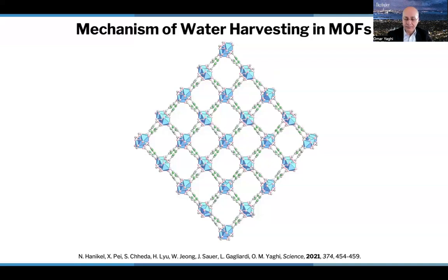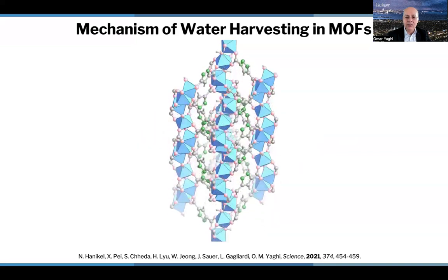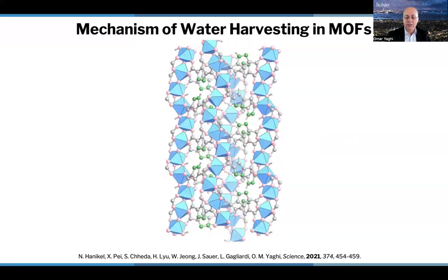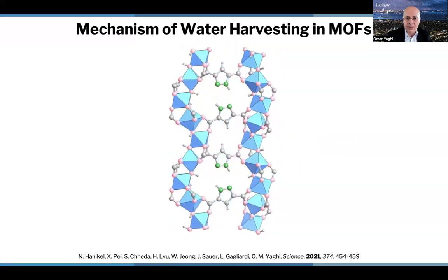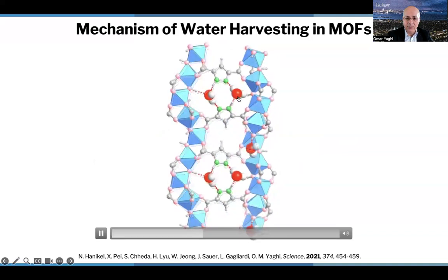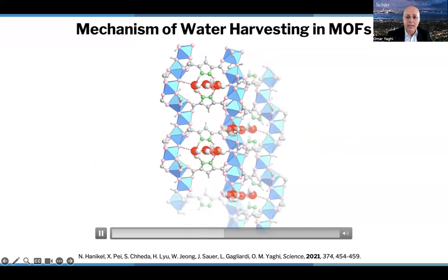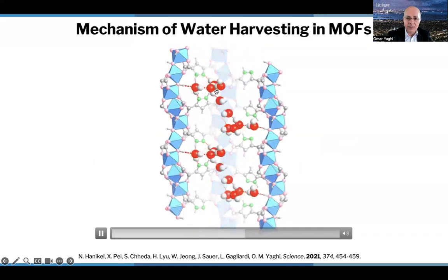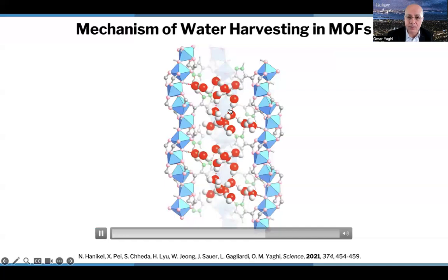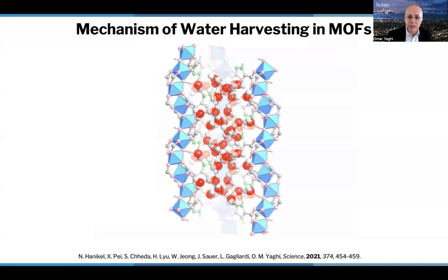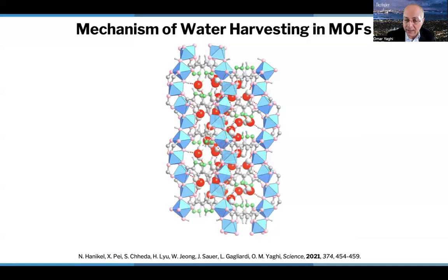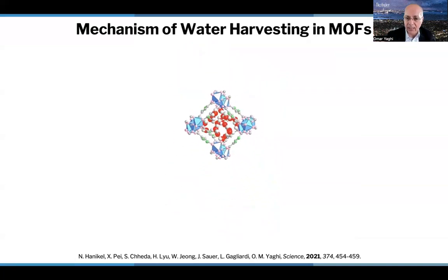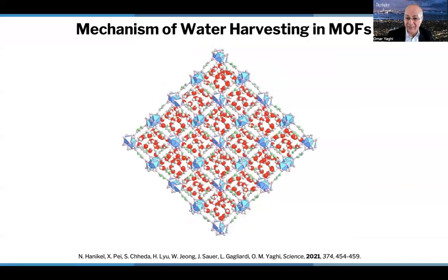And this is how the MOF takes up water. I'm going to just extract one pore and slice it to show you where the water molecules reside inside the structure. And you'll see water going into the hydrophilic sites, first water, second water, third water, and a fourth water. Now, they will bridge over the hydrophobic sites, driven by hydrogen bonds between the water molecules. And as I mentioned, because of the hydrophobic tiling of these pores, you're able to remove the water, in this case, at 50 degrees Celsius.